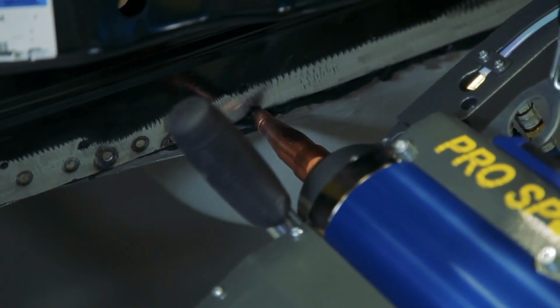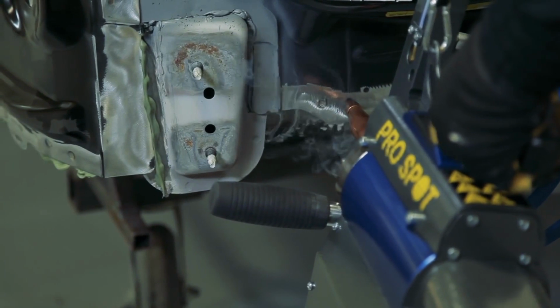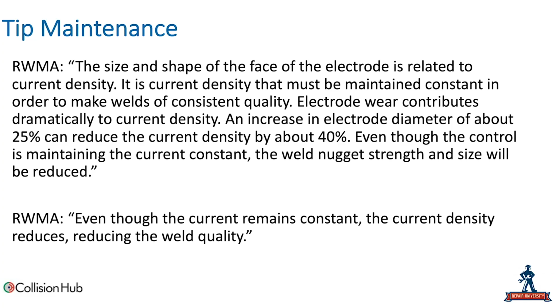I refer to the Resistance Welding Manufacturers Association, and I just want to read a quote that they've got in one of their publications. It says, "The size and shape of the face of the electrode is related to the current density. It is current density that must be maintained constant in order to make welds of consistent quality. Electrode wear contributes dramatically to current density, dramatically. An increase in electrode diameter of about 25% can reduce the current density by about 40%. Even though the control is maintaining the current constant, the weld nugget strength and size will be reduced."